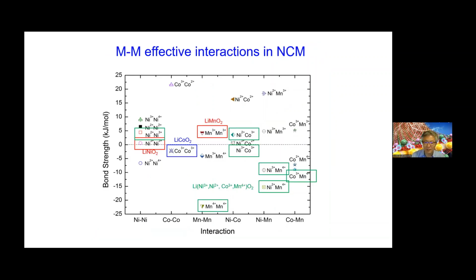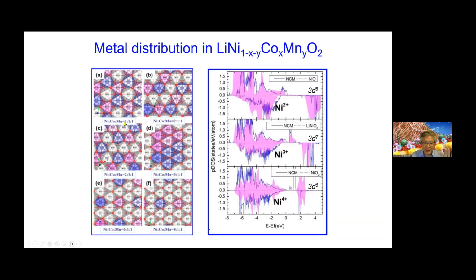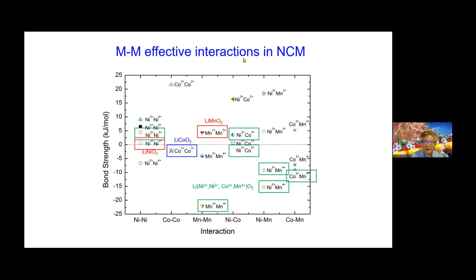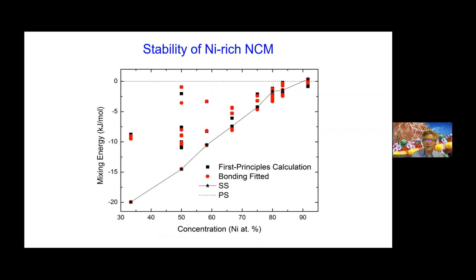So, to address this problem, we have done systematic DFT simulation and careful effective metal-metal interaction analysis, leading to this metal-metal effective interaction in NCM cathode material. Based on that, we can see that some combinations are favorable: manganese 2 plus is favorable, manganese 3 plus is not favorable, nickel 3 plus is not very favorable, nickel 2 plus is favorable. All these are coming out of this. Based on this, we can now map out the stability diagram.